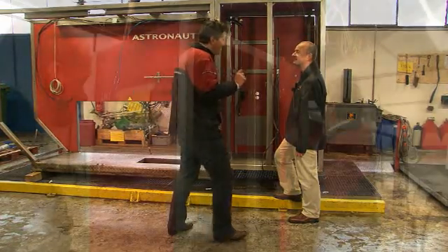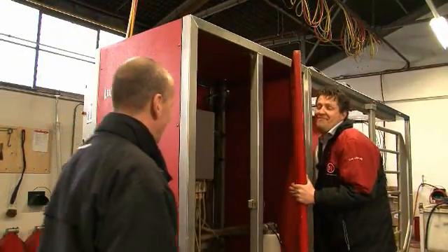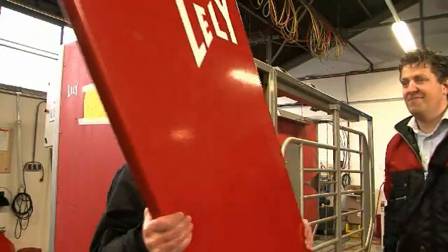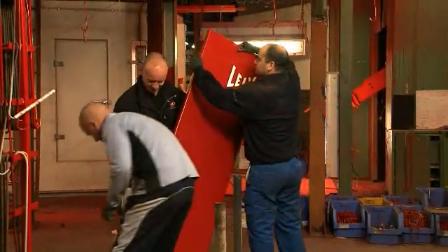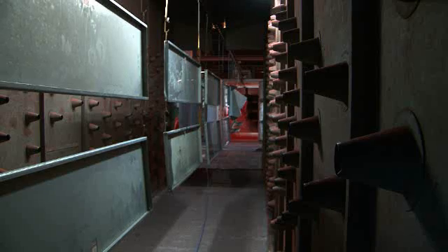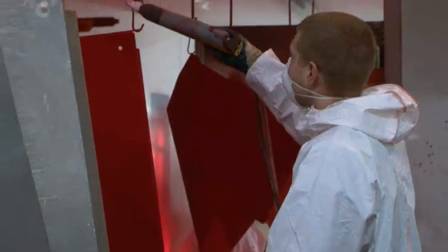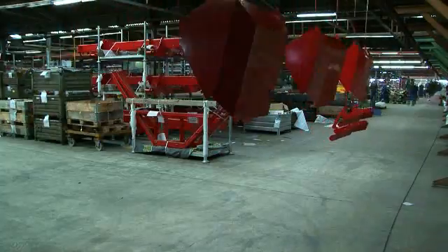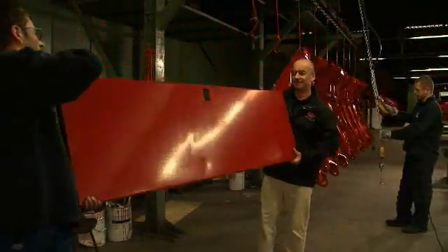All painted parts are taken to the powder coating line. The powder coating station that Lely uses in Maassluis has a length of 380 meters. All parts are shot blasted, rinsed, and treated before they're covered with a powder, then baked in an oven at 250 degrees, resulting in a tough and shiny red coating.